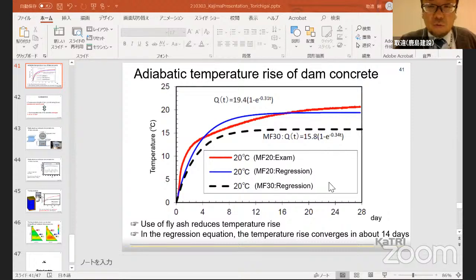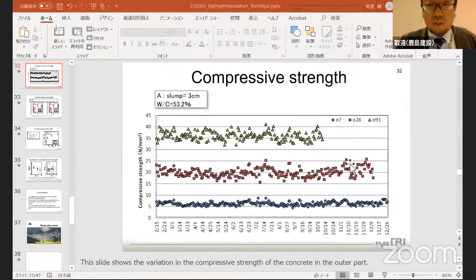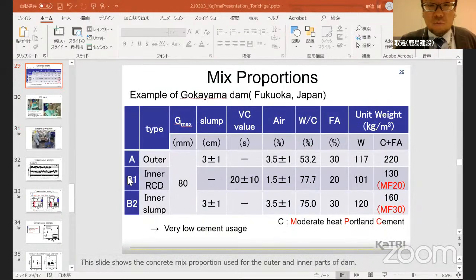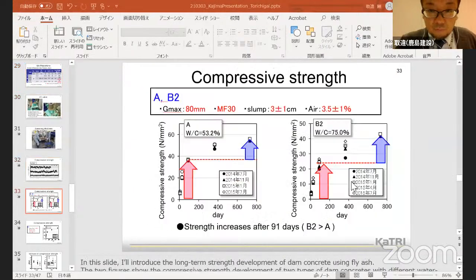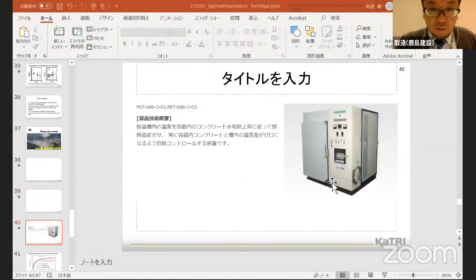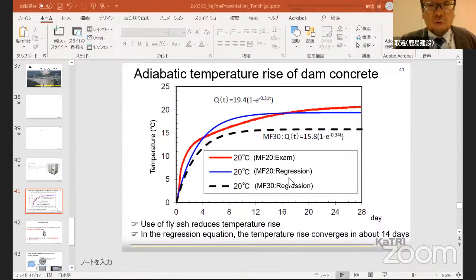In this test, the unit weight of cement and fly ash is 130 kilograms per cubic meter, and we used this RCD concrete. The mixed proportion of the RCD concrete and the adiabatic temperature rise are like this.